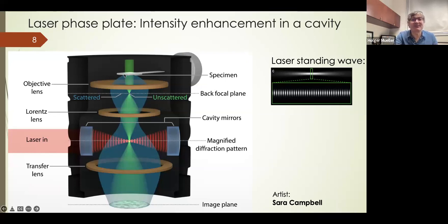So here's a schematic of the microscope. There's the specimen here. Lenses are symbolized by these current loops. There's a focal plane right after the objective lens, and you see the green electron beam has a focal point here, right? But unfortunately, two things prevent us from putting the laser phase plate right here. The first is physical space. The objective aperture is crammed, okay? The second is that the focal length of the objective lens is quite short, 3.5 millimeters in our scope. And that means this unscattered focal spot is very small, making it hard to match the size of the laser focus to the size of the electron focus.